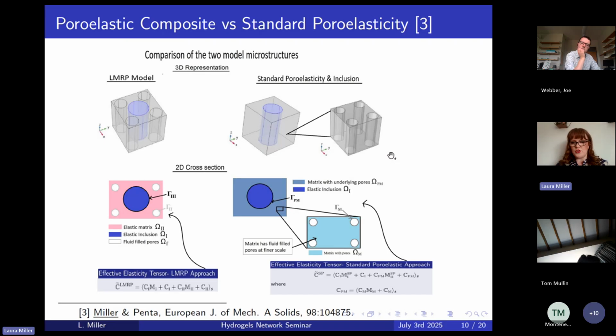But what was there in the literature was models for standard composites where you have two solid phases, or you have those typical poroelastic materials that I mentioned, where our matrix is homogeneous and we have the pores. We wanted to come up with the most comparable way that we could to see what the difference was by having them all at the same scale versus having them not at the same scale. So we decided that we could create a composite where the underlying matrix part was porous. So this is a poroelastic composite. This is a composite with a porous underlying matrix.